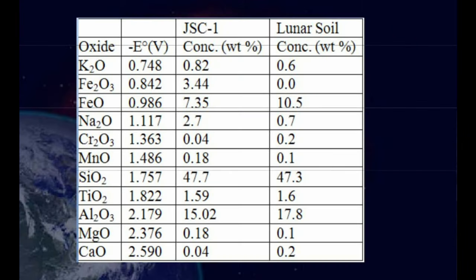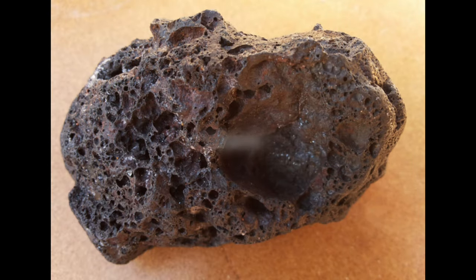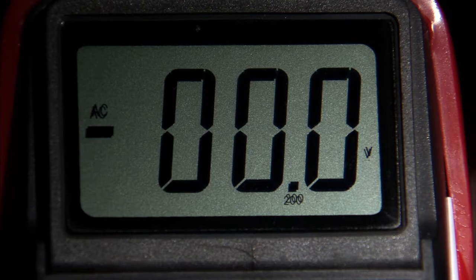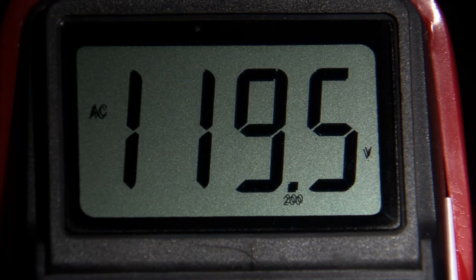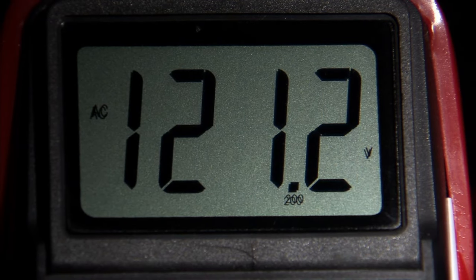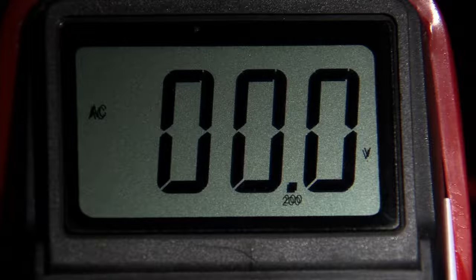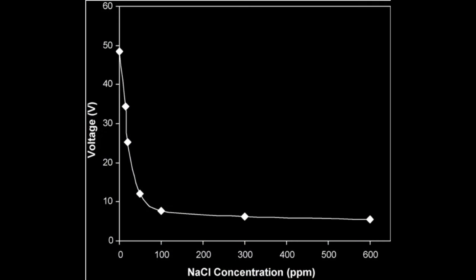But if you use too high of a voltage, say over 2.6, then you disassociate everything all at once and all the iron and aluminum and magnesium and chromium deposit on the same cathode together, and you're left with that crappy alloy cake. It basically robs us of our ability to control the voltages in very slight ways required to pull out elements one at a time. But we have a solution, pun intended. We add ions to the regolith by dissolving it in a molten salt, typically calcium chloride, which will decrease the resistance and lower the necessary voltages needed for selective reduction.